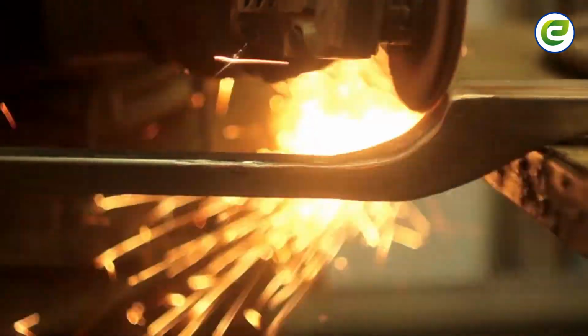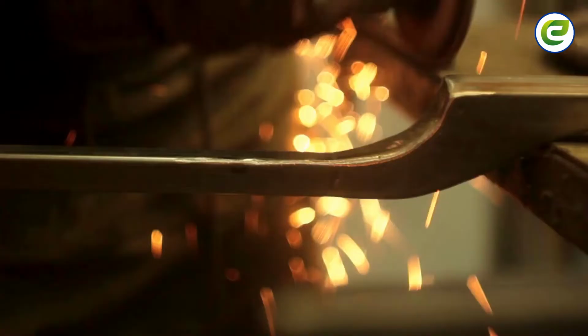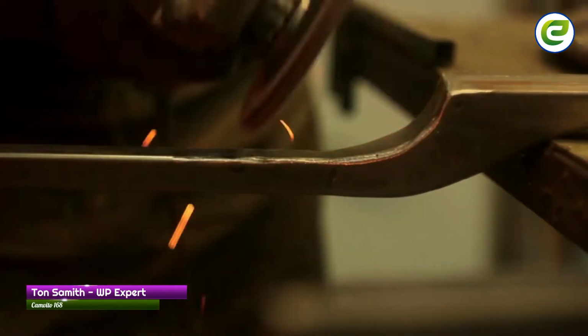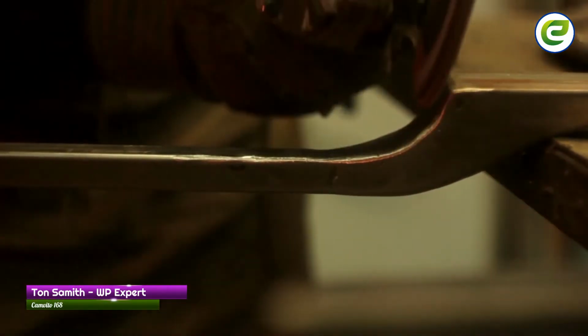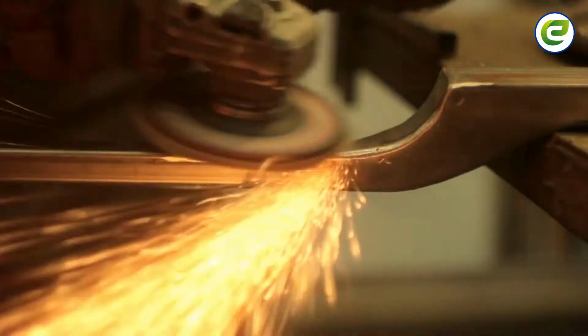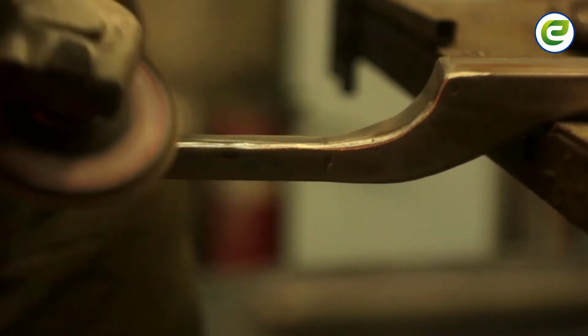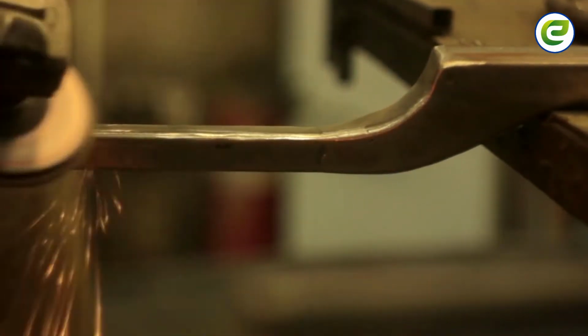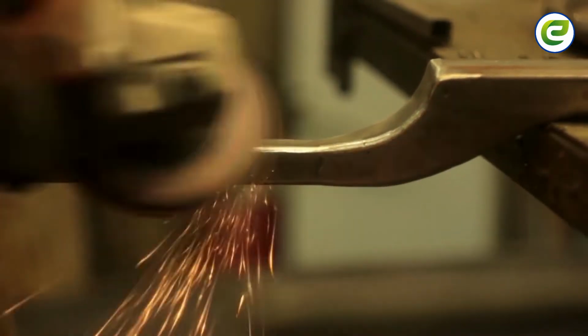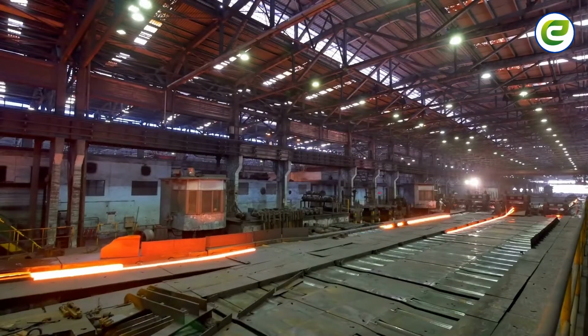Duplex stainless steel was developed during the 1950s to meet the needs of the chemical industry for high strength linked to corrosion resistance and wear resistance. These alloys have a microstructure consisting of about half ferrite and half austenite and a composition of 25% chromium, 5% nickel, 3% copper, and 2% molybdenum.